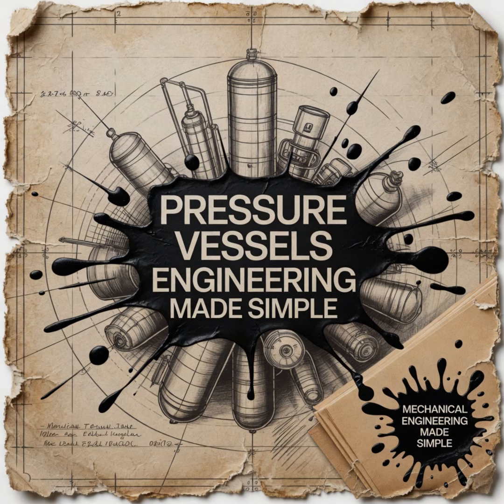Why is the number 10 the magic threshold? What changes mechanically at that point? It's about how the stress distributes through the metal. In a thin-walled vessel, we assume that the membrane stresses, which are the forces acting tangentially to the surface, basically pulling the metal apart like a stretched balloon, are completely uniform across the entire thickness of the wall. So the inside skin of the steel and the outside skin of the steel are experiencing the exact same amount of tension. Exactly. Because the wall is relatively thin, we can also mathematically ignore the radial stress.